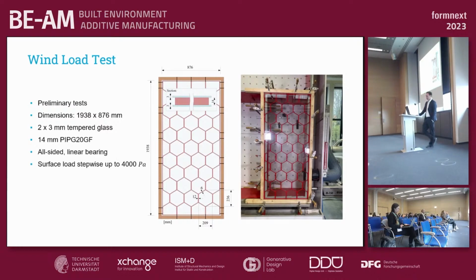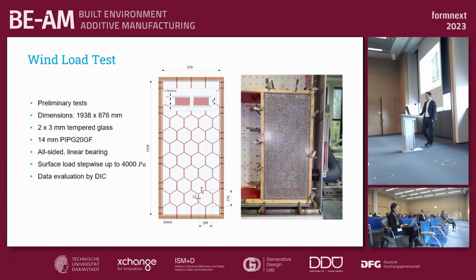And yes, the whole test specimen was supported on each side, and we can blow in and suck out air into the cavity behind the facade element. And we test the element up to 4000 Pascal, which is still quite a lot. If you would want to calculate the facade panel, you would estimate in Germany, as far as I know, 1500 Pascals. So it is a really strong wind load on this panel. And we tried to measure everything with the DIC system, the digital image correlation system, so that we get deformation and displacements from the panel when it is loaded.